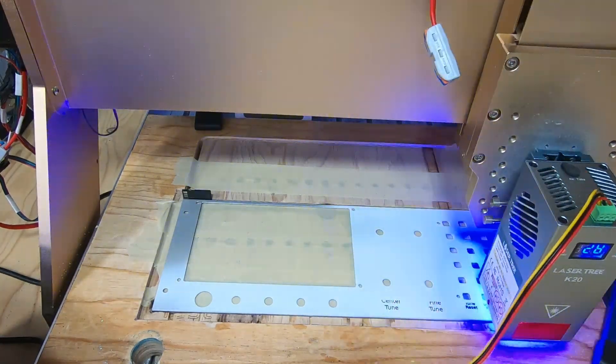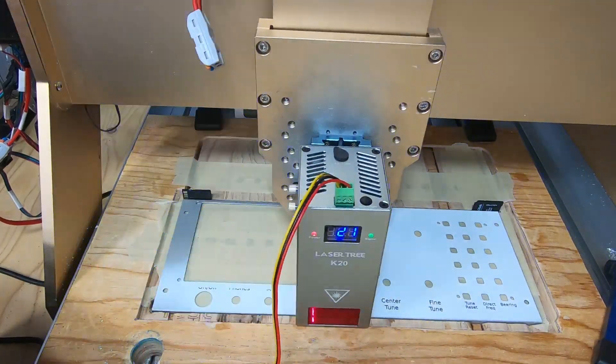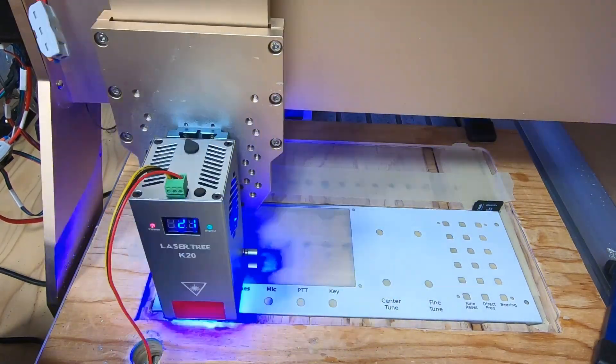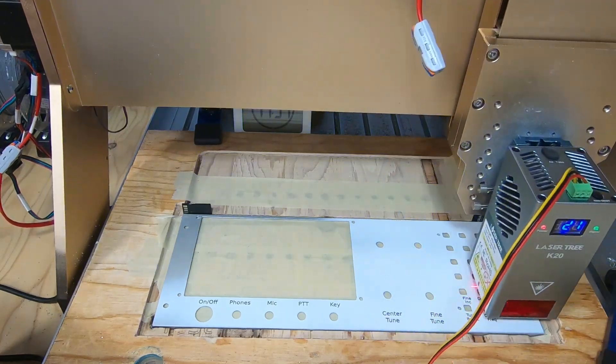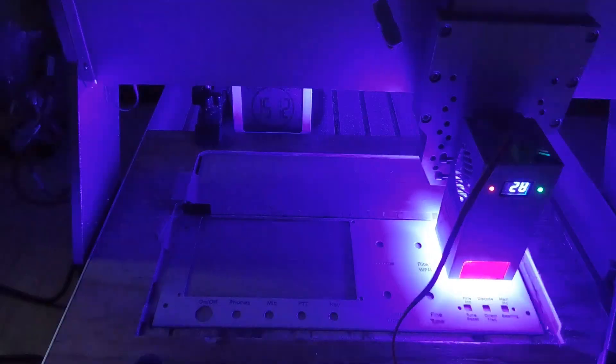The marking is very dark and durable. I actually made a mistake with one of the panels, so I had to remove the markings and etch and anodize again. It took over an hour of power sanding and chemical etching to remove the markings — I was quite impressed with how tough this product is. I have no affiliation with Brilliance Laser Ink; this is actually my first time using their products, but it is an incredible product that I highly recommend. The footage of the first etch is sped up 100 times — that front panel took two hours to etch. This step is a lot faster but still takes a while; this footage is sped up 50 times and takes about an hour on the front panel.